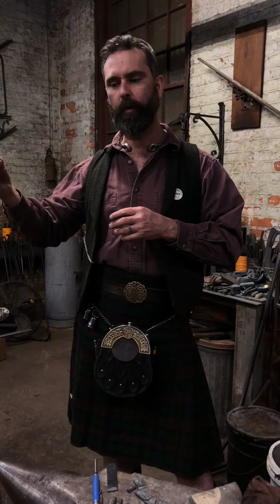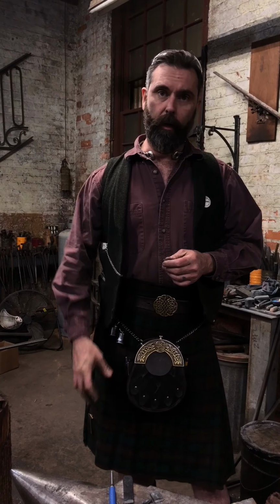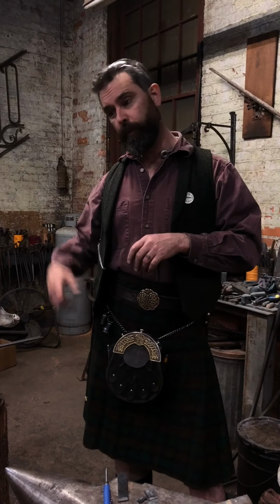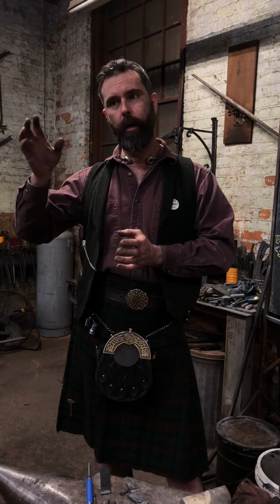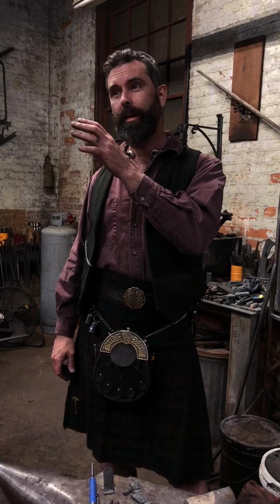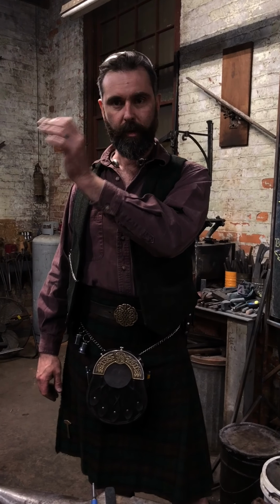And the idea is always to produce a product which has the best capabilities you can possibly give it. So learn your steel, learn what it does for you. If you're forging a blade and you find that steel X requires 3 normalization cycles in order to bring it down to the finest grain structure that you can get it to, give it those 3 normalizing cycles. And if you find that you get better results by doing those cycles in a heat treat oven, do them in a heat treat oven, because you're going to get better results. And at the end of the day, it does not affect the hardness, it merely affects the toughness. And toughness often is what we're trying to gain, even if the hardness is high.